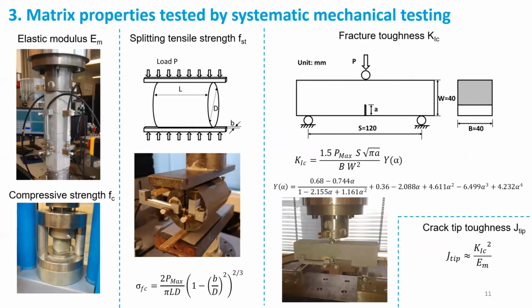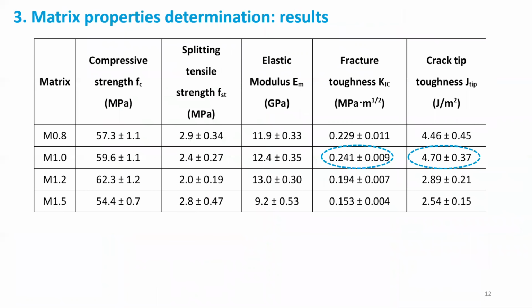The matrix properties are tested using various experiments. This includes the elastic modulus, compressive strength, and we tested splitting tensile strength as the first cracking strength of the matrix. We also determined the fracture toughness, K1C, and combined with the elastic modulus, we can calculate the crack tip toughness, J-tip, which will be further used for the PSH indices. So the matrix properties are shown here.